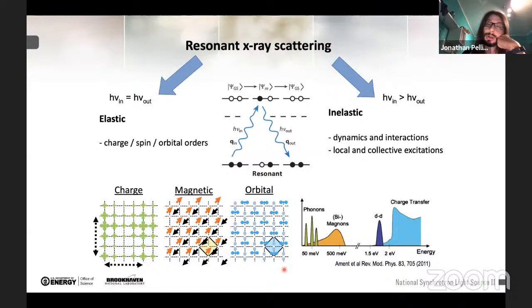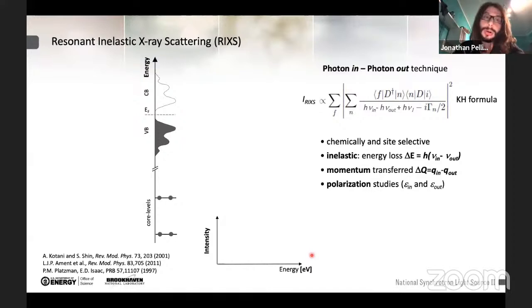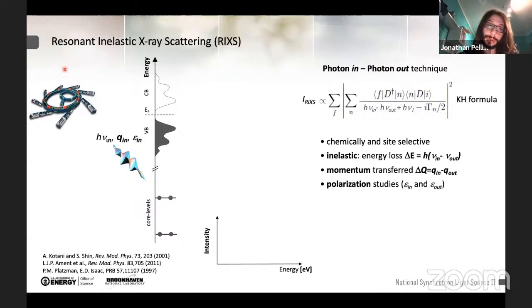But now let me try to go a bit deeper into what resonant inelastic X-ray scattering is. So RIXS is a photon-in, photon-out spectroscopic technique where we normally use synchrotron radiation to produce a tunable incident X-ray beam that selects the absorption energy of our material. In our material, if we were to draw the energy levels, we have at low energy the core level, we have the valence band, the Fermi level, and an empty conduction band.